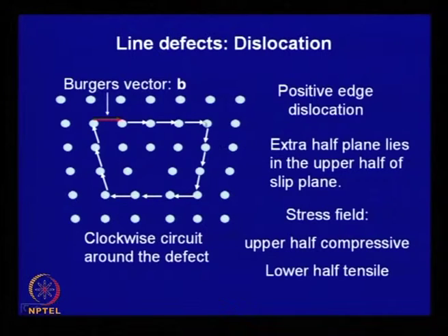Now, but look at it overall. What you have is a missing plane here. In that case, the lattice will be a little distorted, something like this. This distortion represents a kind of stress field. It is an indication of a stress field. The lattice is strained. This point, which represents a line, is called dislocation, and this type of dislocation is called edge dislocation, which you can visualize in crystal lattice terms as an extra plane of atoms here.